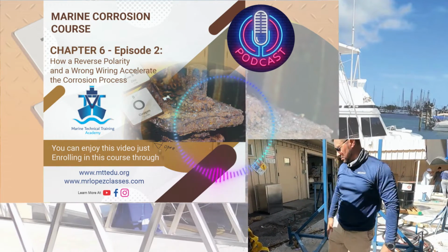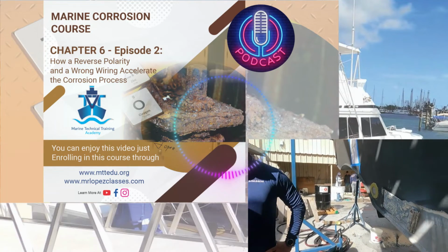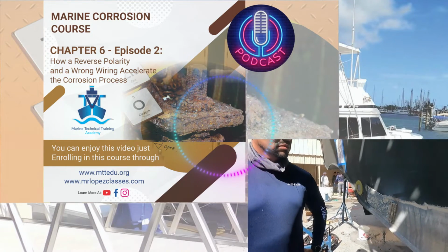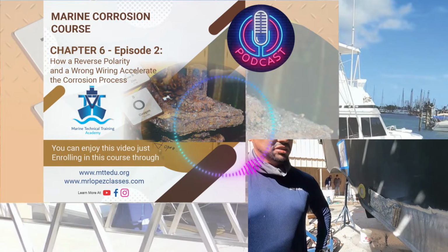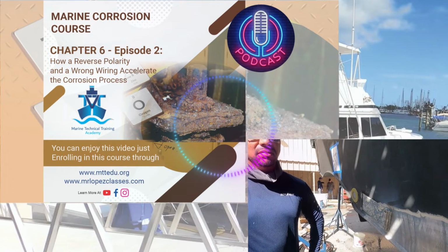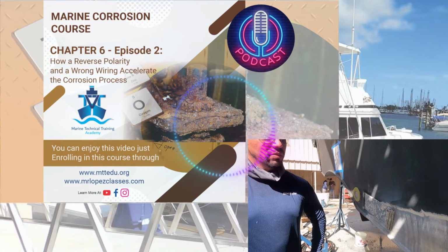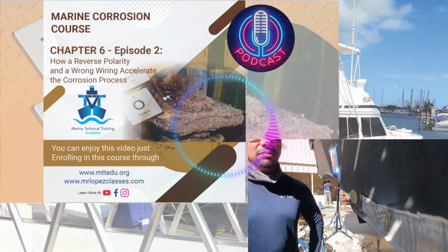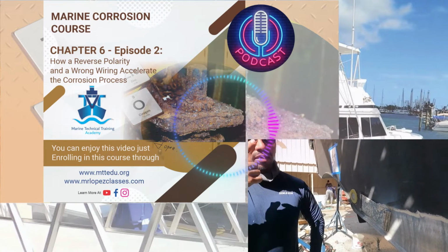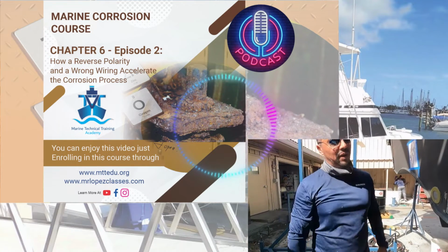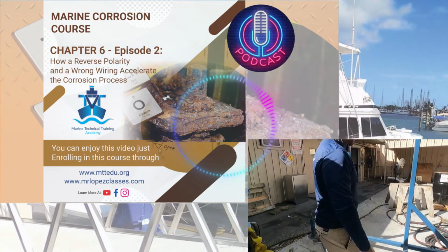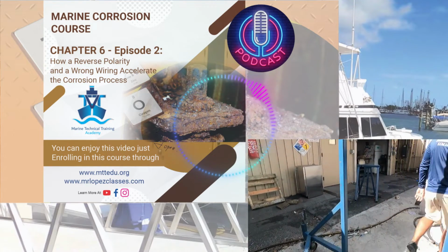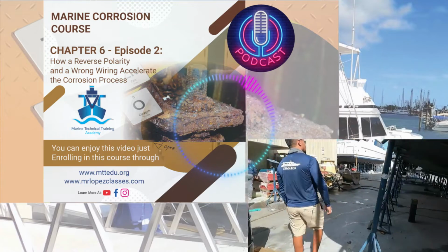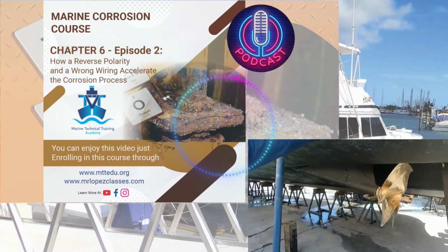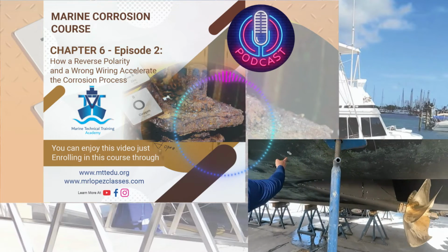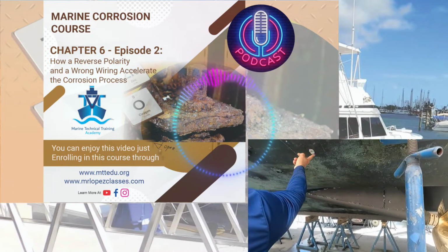Explain to him that when your boat is normally docked in your home, you don't have problems of corrosion. Your boat is clean inside. All the blocks, the motor, generators, the air conditioning equipment, everything is clean. But you moved your boat to the marina 2 weeks ago, and right now everything is corroded. And you checked the ground in the pedestal, and you found that difference, more than 2 volts. That's the reason. Alright? I hope you are clear with that concept.